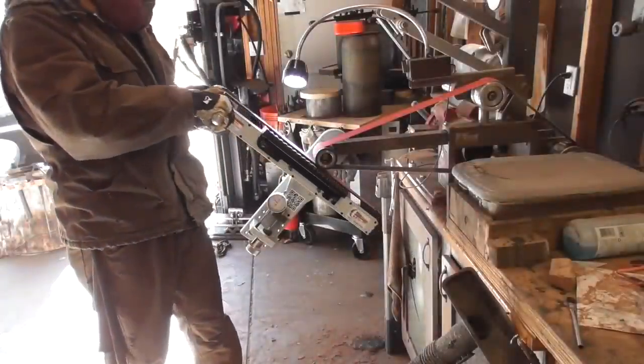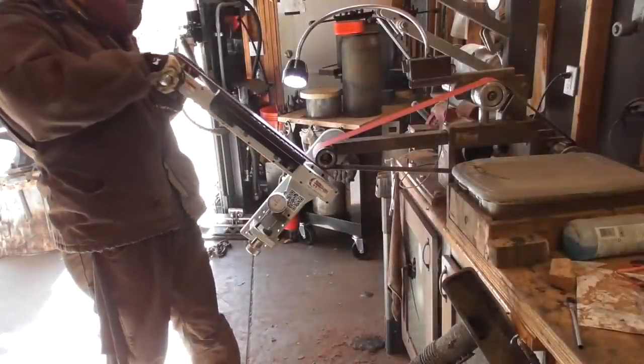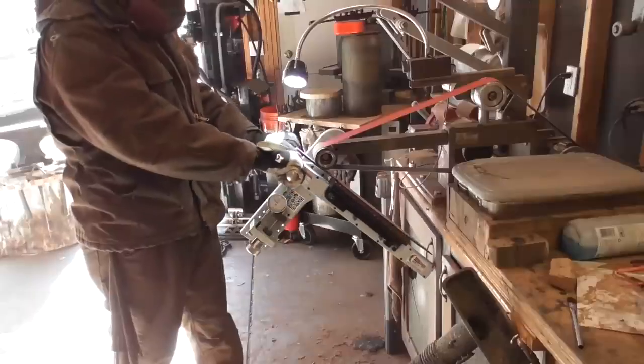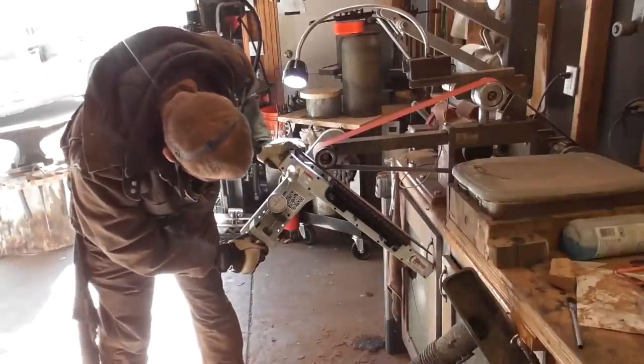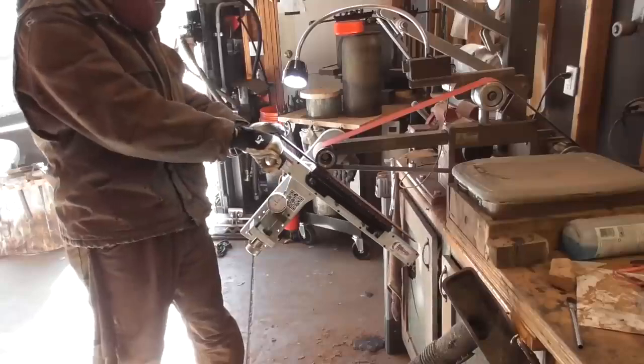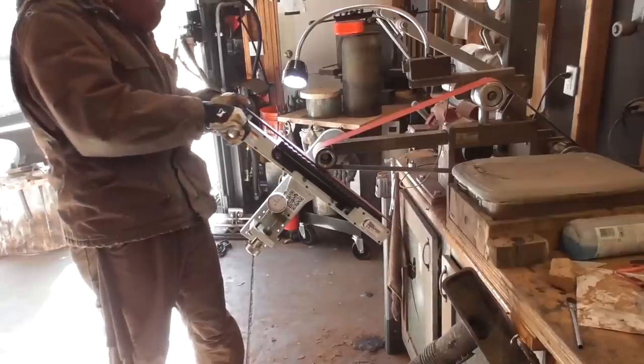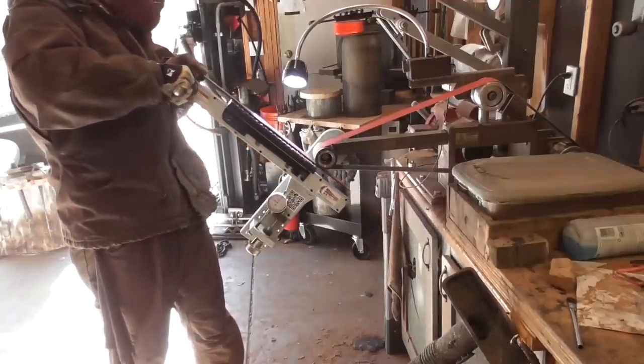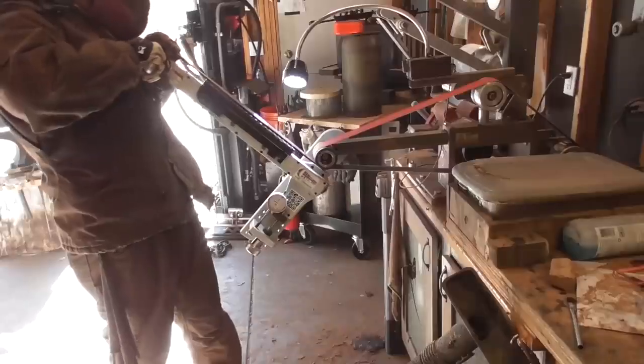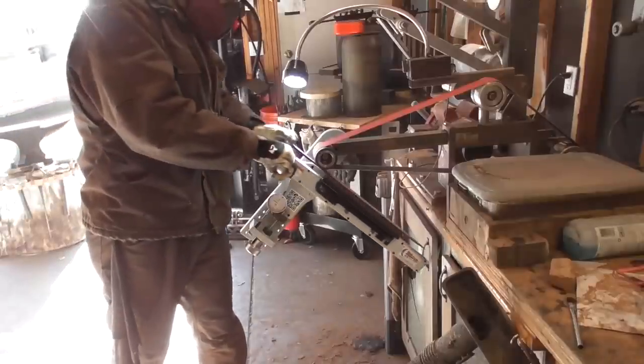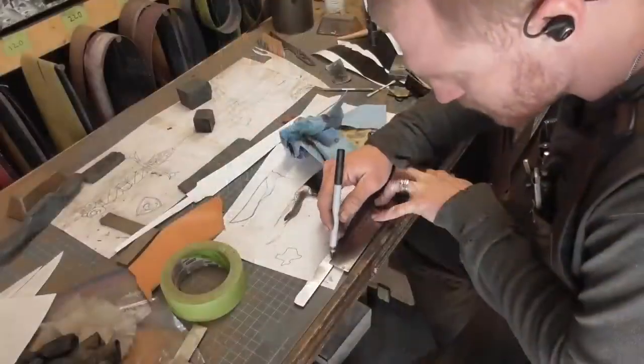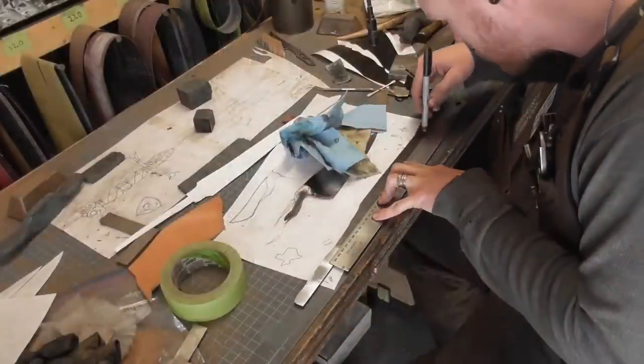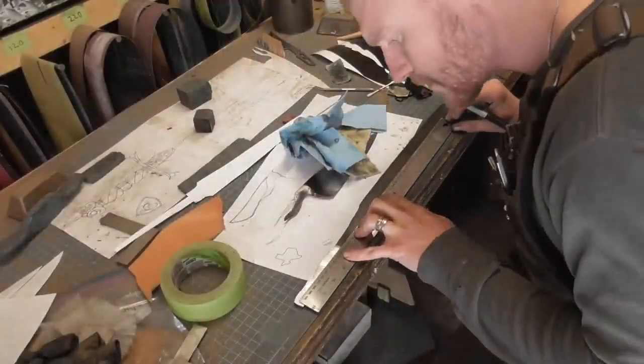So I start by grinding off the big scale, and now I'm taking it over to my surface grinding attachment and making sure that the entire blade is going to be perfectly flat so that I can go ahead and work from there. It's important to have a flat blade so that everything is perfectly in line and symmetrical with the center lines. You can see me drawing out that center line right here.